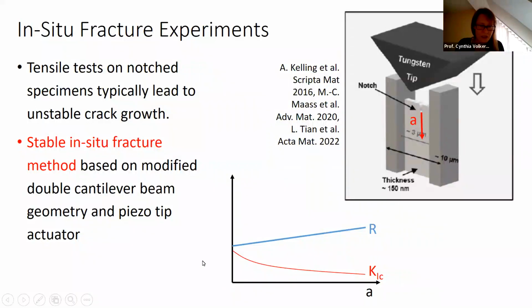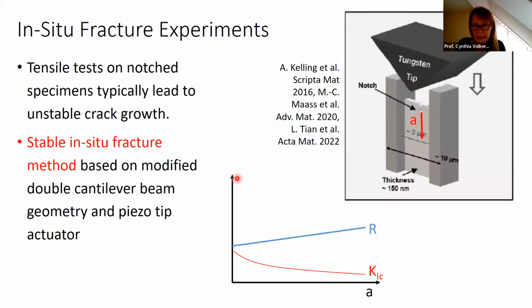Now, the advantage of this geometry is that the K1C, the stress intensity factor, decreases in this case as you move down, just simply due to the bending moments of the 2 cantilevers at the side. So the geometry just makes it harder. We have to push harder to pry this apart, and that allows us, in a very simple way, much better control over propagation of the crack. And that's the trick we use here. And it's been used for a variety of different studies over the years, where we started out without the hydrogen to make our life easier, but our goal was eventually to get to these studies that I'll present today.